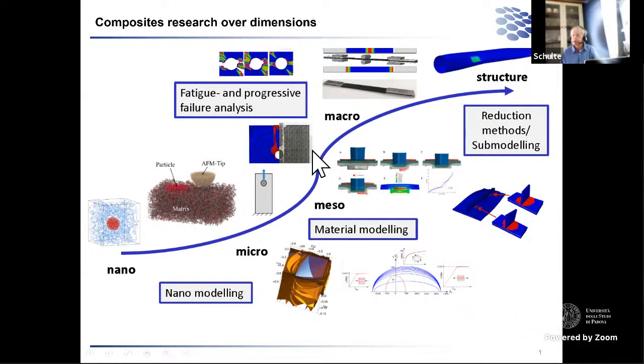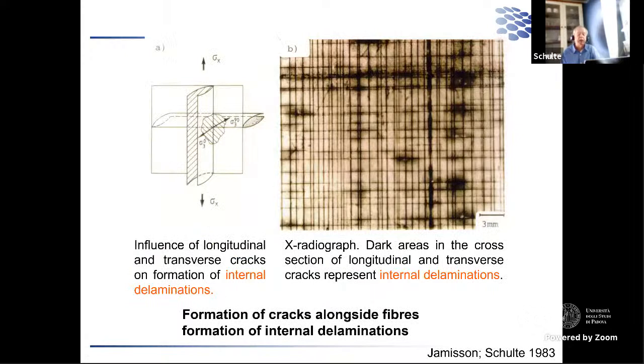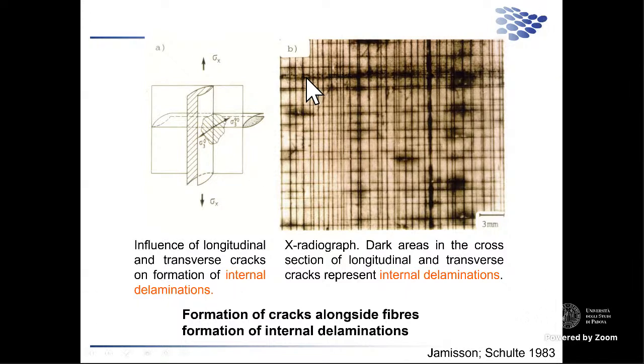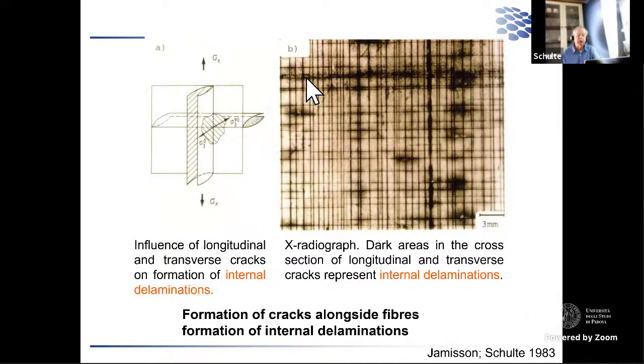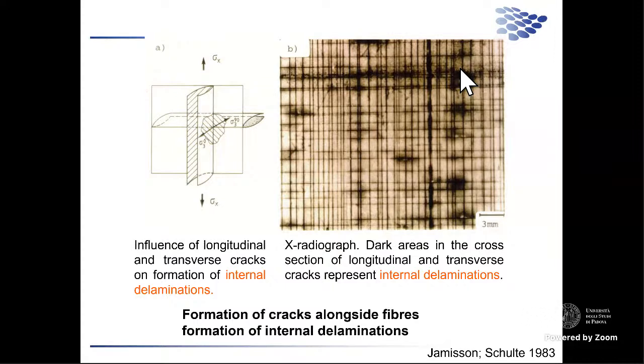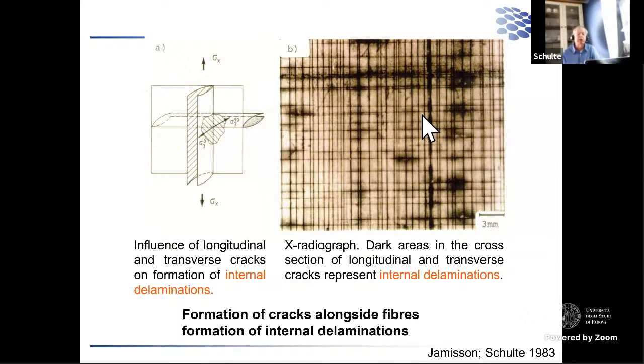But what gives now X-ray tomography? And maybe we go forward now to the next slide. That means in the past, when we wanted to understand damage in a composite material, then we had to make X-ray photographs, as you see here, and this X-ray radiograph is from a cross-ply polymer. In order to see damage, in this case, cracks or internal delamination, something already talked about this morning, then we had to use an opaque that penetrated into a damage. And once it was in there, then we could see that in an X-ray.